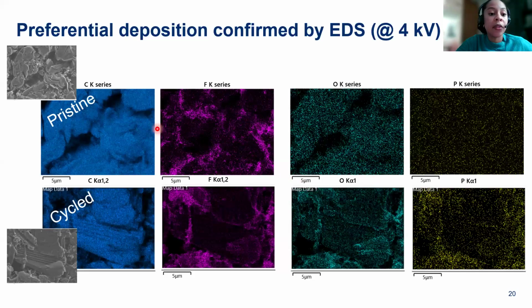So for pristine, we see carbon all over, of course. And for fluorine, we have some fluorine that is native in the material because of the binder. But we again see some fluorine starting to accumulate on the sample edges, but not much on the basal plane. We see a more distinct oxygen signal on the sample edges as well. And we also see, especially with the fluorine, a much increased signal of phosphorus when we look at the sample that has been cycled. So this also correlates very well with the NanoSIMS images.